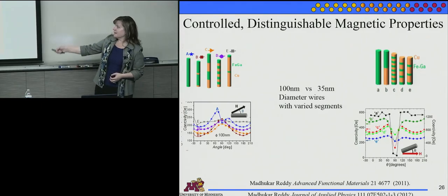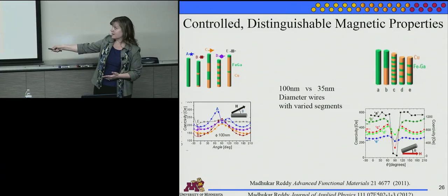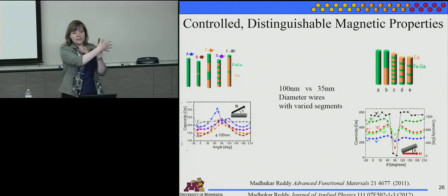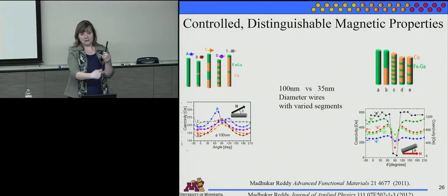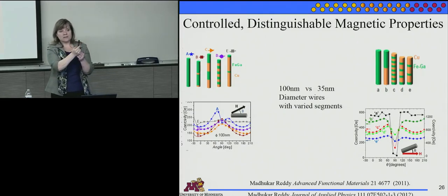Now this is not exactly coherent rotation either because it actually should look like this smooth sine wave, only have a maximum at 0, minimum at 90, and a maximum at 0. So what we think is we're just not getting the same mechanisms for all the different angles we're applying the field at. But at 90, we're pretty sure we're having coherent rotation because you apply the field this way, you force all those moments to come out in the direction they really don't want to go because the shape anisotropy is along the wire. So when you take the field away, the moments rotate where they want to be.